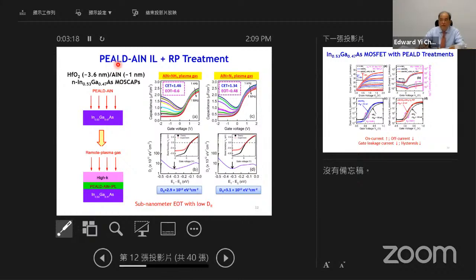And then to further reduce the EOT, we move to hafnium oxide, aluminum nitride. In this case, hafnium oxide is 3.6 nanometer, aluminum nitride is 1 nanometer. And we use this as the high-K material. And then after that, we do remote plasma gas treatment. Okay, in that one, we can improve the interface quality. So with aluminum nitride and ammonia plasma treatment, we can reach EOT 0.6. And we also try with aluminum nitride and nitrogen plasma treatment. And in this case, we can get EOT at about 0.48 with CET around 1.34.